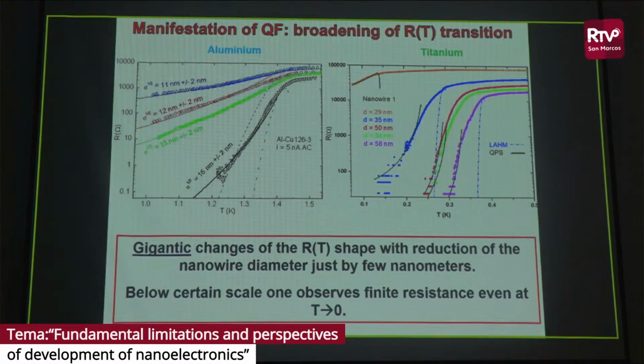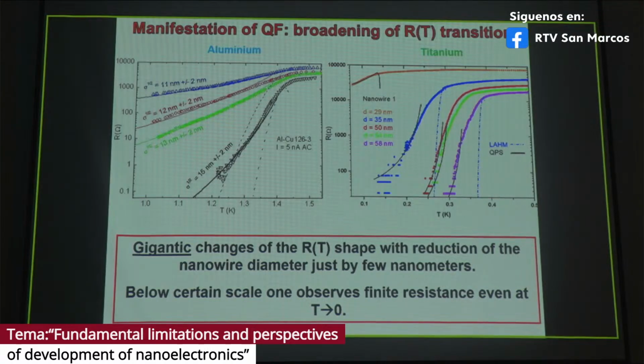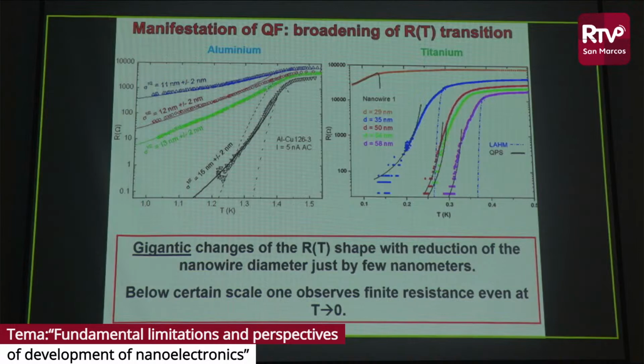So here are the experimental plots we obtained some time ago. Let us, for concreteness, look at the left image, which shows the dependence of resistivity versus temperature for an aluminum nanowire. Initially, it had a cross-section of about 15 nanometers. Then we reduced the dimension by just 2 nanometers, and we go from black to green dots. Then one more nanometer, brown dots. And you can see that there is no way to understand such behavior using just Ohm's law. It's the impact of quantum fluctuations. And for sufficiently thin nanowires, the resistance does not extrapolate to zero. So a very narrow superconducting nanowire will never show DC zero resistance.